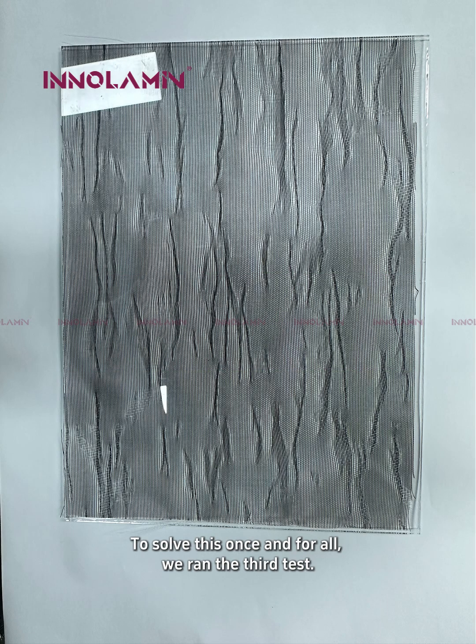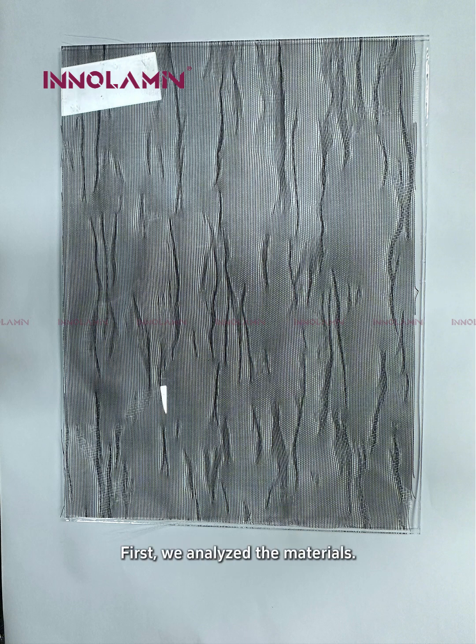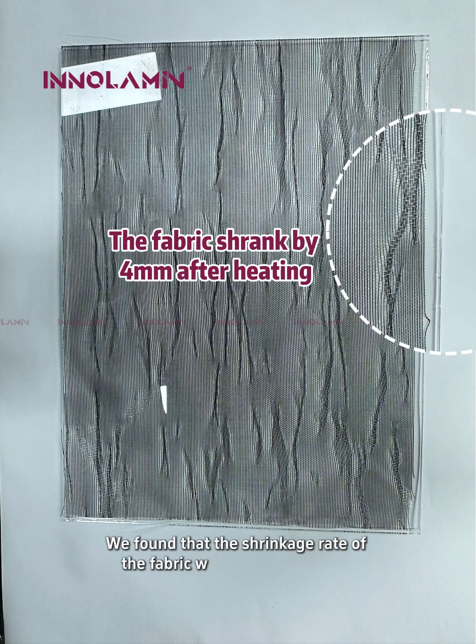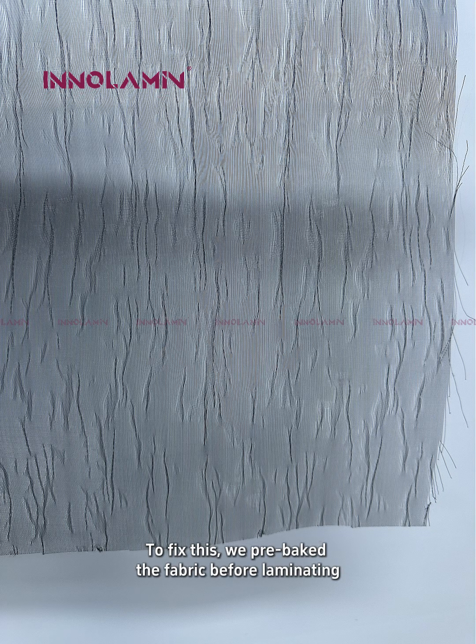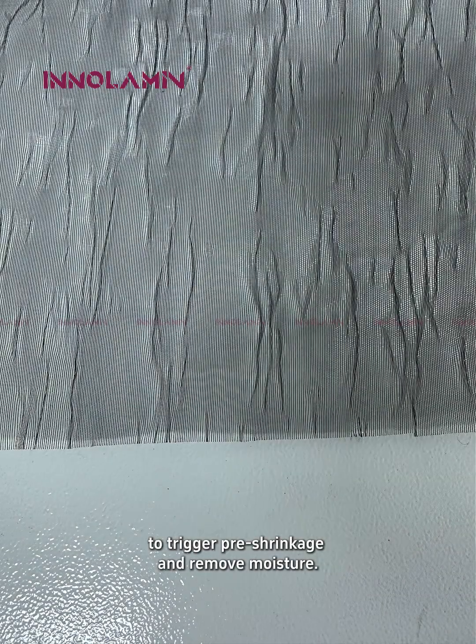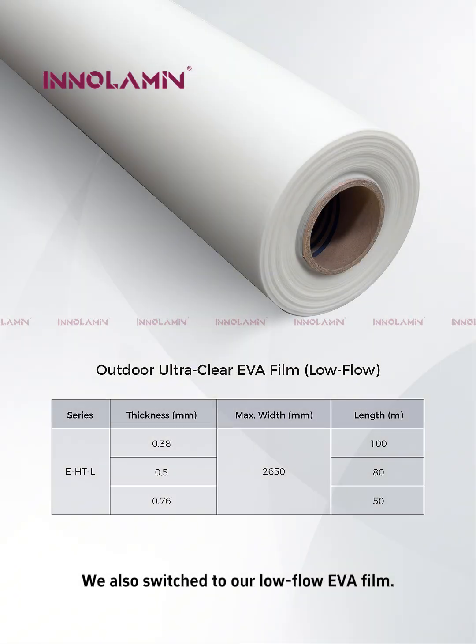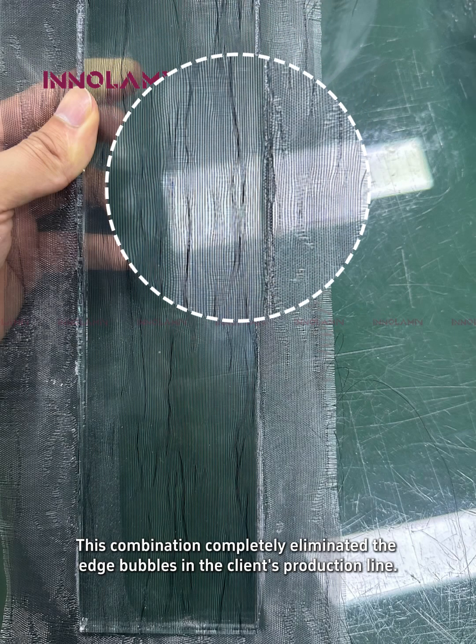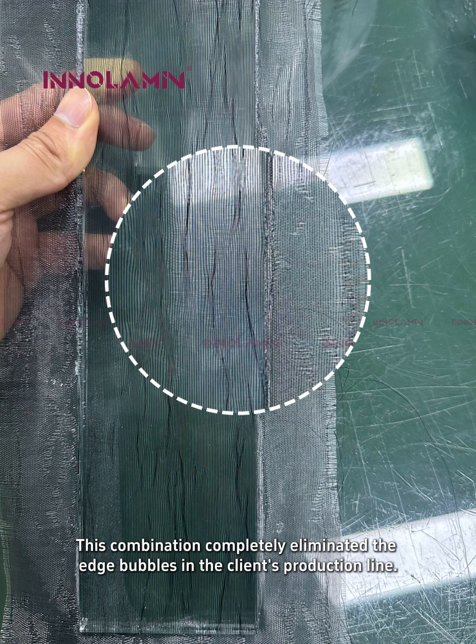To solve this once and for all, we ran the third test. First, we analyzed the materials. We found that the shrinkage rate of the fabric was as high as 3 to 4%, and the moisture content was also too high. To fix this, we pre-baked the fabric before laminating to trigger pre-shrinkage and remove moisture. We also switched to our low-flow EVA film. This combination completely eliminated the edge bubbles in the client's production line.